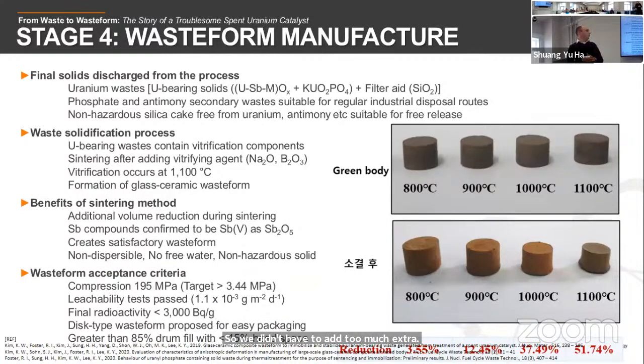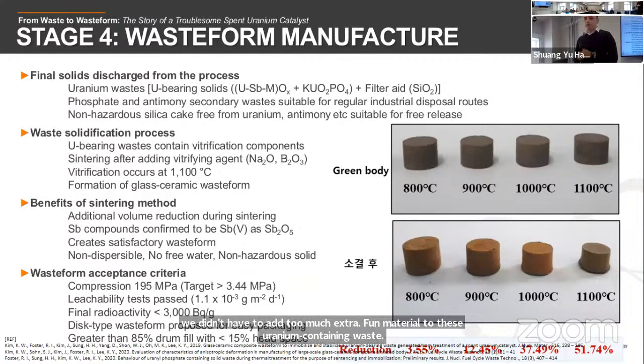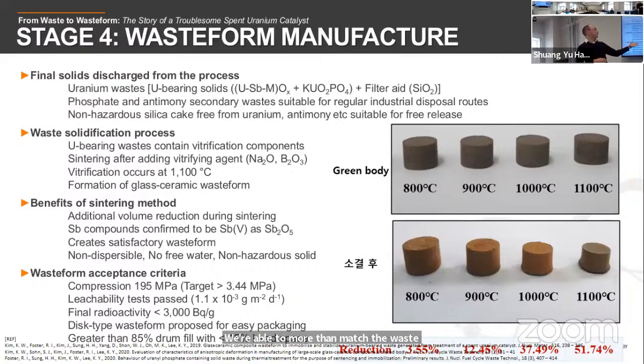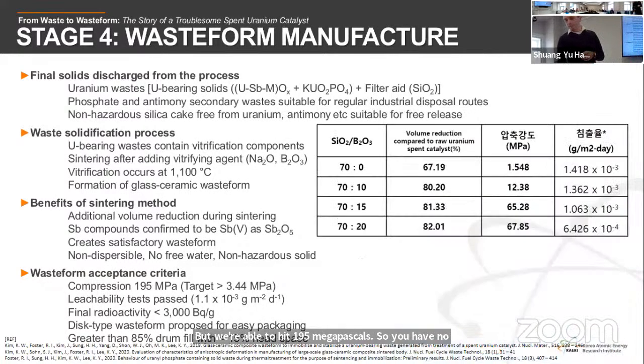We were able to more than match the waste form acceptance criteria. For example, compression testing for disposal at Gyeongju requires 3.44 megapascals, but we're able to hit 195 megapascals, so we had no issue there, along with the leaching and the final radioactivity of 3,000 becquerel per gram.